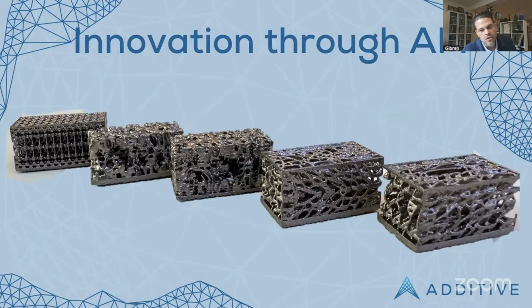So we spent 2 years. We researched more than 30 lattices in total and did a deep dive with a reasonable team of engineers and researchers. These are some of the lattices we printed in cubes. We then established a facility with everything in-house to test modulus of elasticity, to test capillary action, like can it wick blood up, to test how dense it is, to test total porosity, all of these metrics that we said will make the ideal spine implant. We just went and we didn't stop until we found what we thought were the ideal lattices. So these are some of the examples of the prints that we did, looking at an organic structure, looking at that sort of trabecular style.